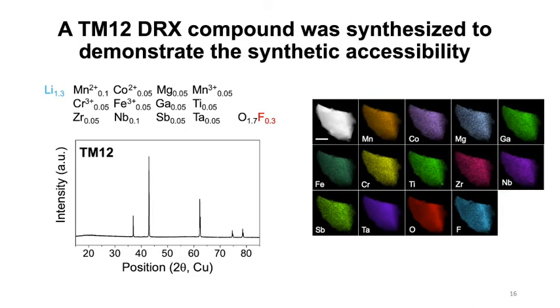And based on our compatibility analysis, we successfully synthesized a DRX compound that contains 12 different transition metal species, including manganese 2+, cobalt 2+, magnesium, manganese 3+, chromium, iron, gallium, titanium, zirconium, niobium, antimony, and tantalum. The XRD pattern shows that it forms a pure DRX phase with no observable impurity. And also the TEM-EDS mapping shows that all the elements are distributed uniformly in the lattice.